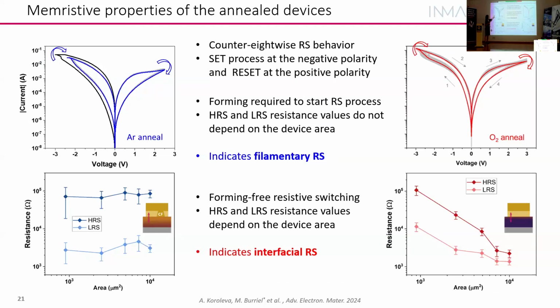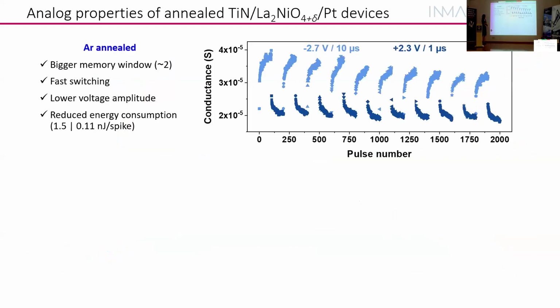The devices behave very differently if we did an oxygen anneal. We have a higher concentration of oxygen. The material is more conductive. And instead of having this filamentary type switching, we have interface type switching that we can see by no big jump in the curves and by this area dependence of the resistance.